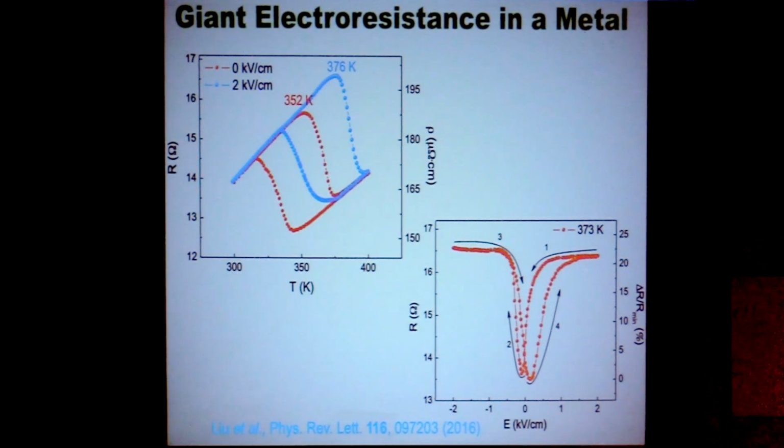As a result, the resistance of this intermetallic alloy changed quite a lot. For example, here at 100 degrees Celsius, the resistance changed by like 22%. Consider that this material system has a very large carrier density of 6 times 10 to the 22 per cubic centimeter.